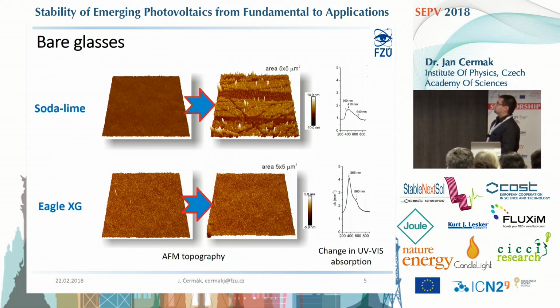In the case of glasses, for both types, we observed an increase in absorption. And in the case of soda-lime glass, we could also see on the surface, here is the image by atomic force microscopy, that some microcracks are created. We think they are the result of local heating of the irradiated area. They are not present in the case of the Eagle glass, most probably because this type of glass has a lower thermal expansion coefficient.